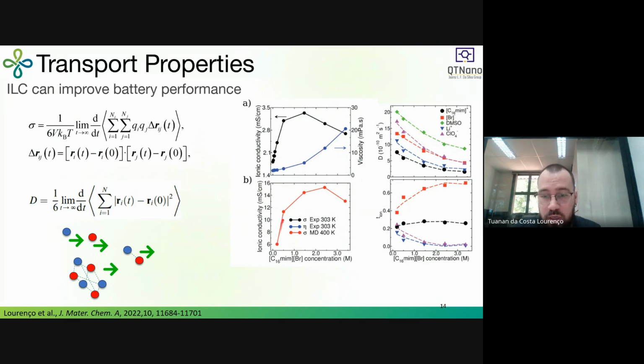However, if we look here, we have the same qualitative agreement. We see the increase and the decrease. And what we are always looking for is the qualitative behavior. If I can describe the qualitative behavior of the experimental data, this means that I can describe the physical chemistry of the material. So my data is agreeing with the experimental behavior.